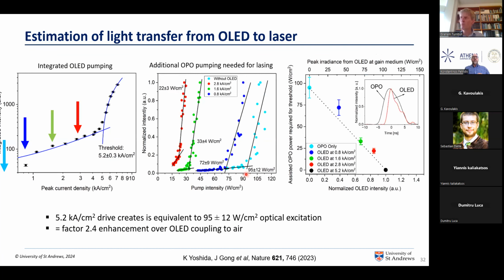And so from this, we can look at the amount of drive we're using from our OLED against the amount of additional power you need from the OPO, from the laser, to pump the organic laser above threshold. And from this, we can estimate that the peak irradiance from the OLED that will make the device work under only electrical drive is around 95 watts per square centimeter.